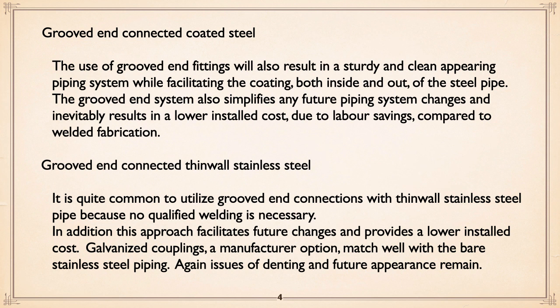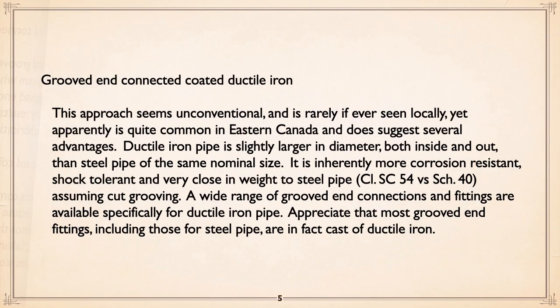Grooved end connected thin wall stainless. Same idea that if we go to thin wall now, we don't need qualified welders because we're not welding it. And again, future changes are possible. And you can get galvanized coating from the groove connecting people, which matches up nicely. But again, denting and the future appearance turning to gray is an issue.